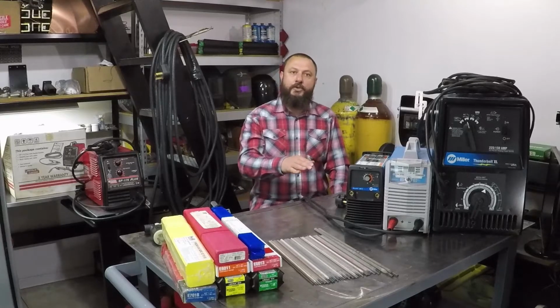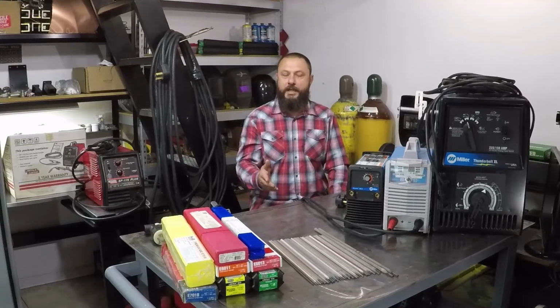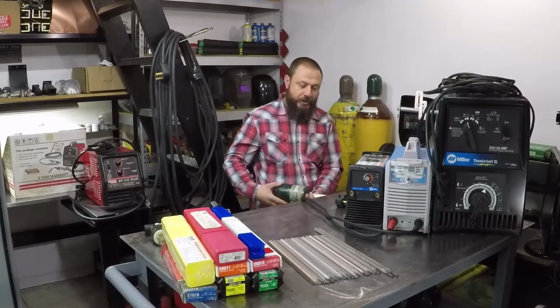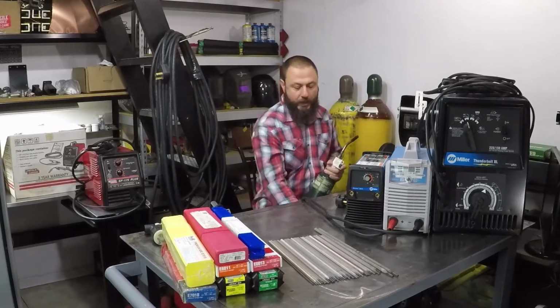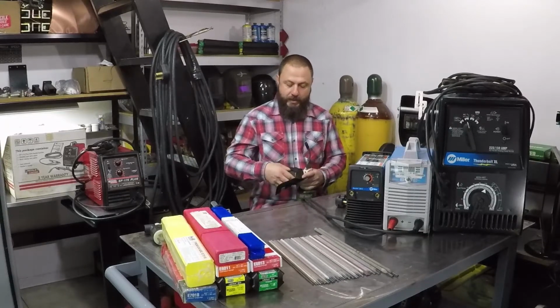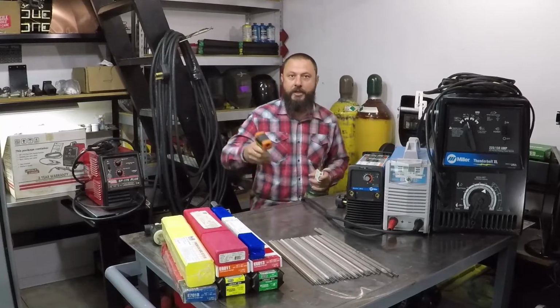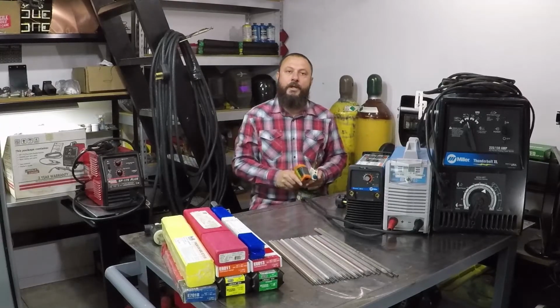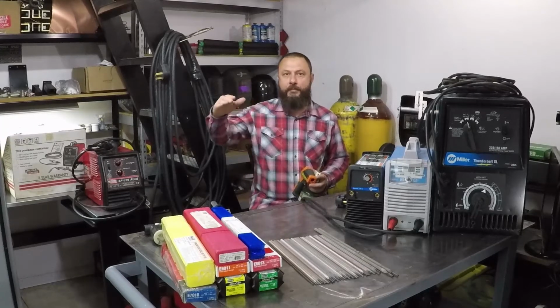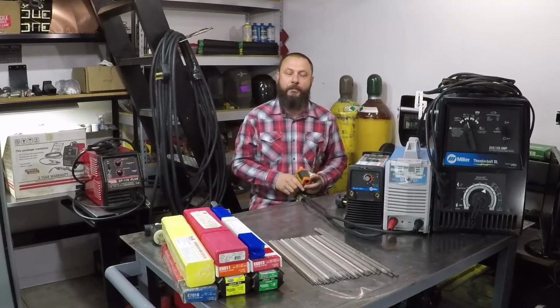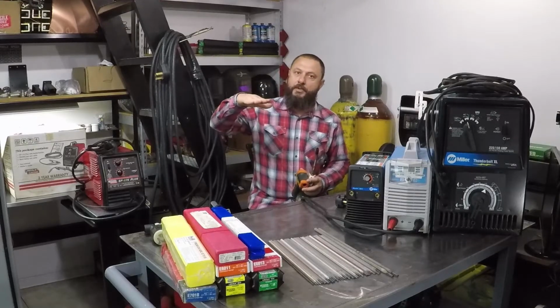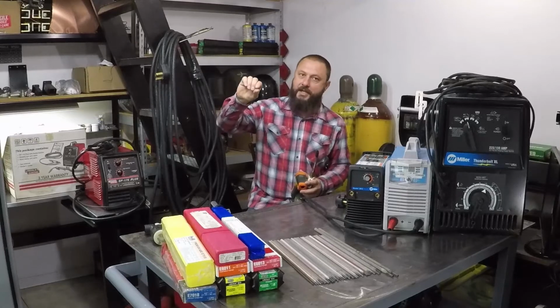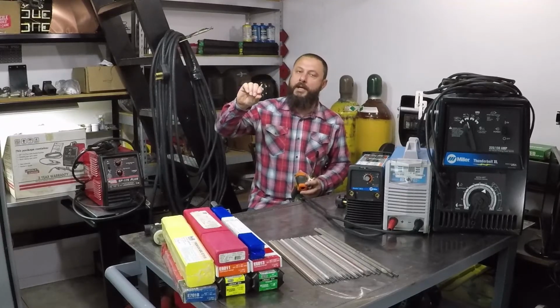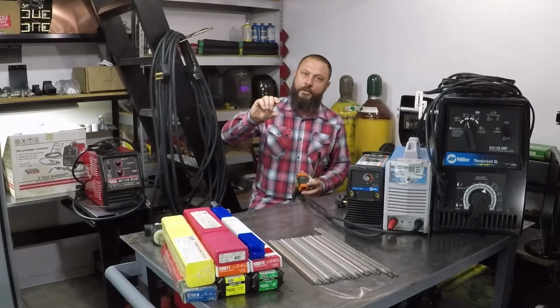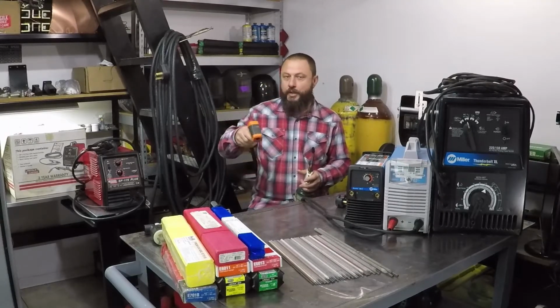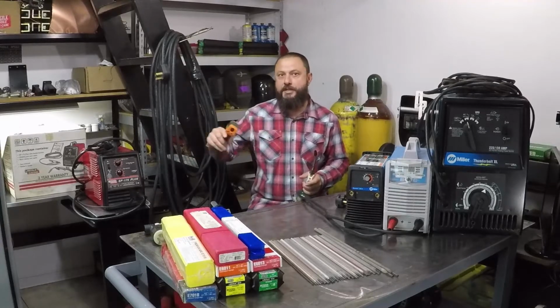With arc weld, you could weld aluminum. The aluminum requires the preheat. You need to heat the aluminum until it reaches a certain temperature before you start to weld. If you do that, make sure you get a gauge to measure the temperature of the surface, because with aluminum, if you overheat the metal, it will deform and you will have a dip on the surface. When aluminum meets oxygen, it forms a crust, a very thin layer on top of the aluminum, that requires more temperature to melt than the aluminum itself. So you have to make sure the aluminum reaches that temperature before you start arc welding.